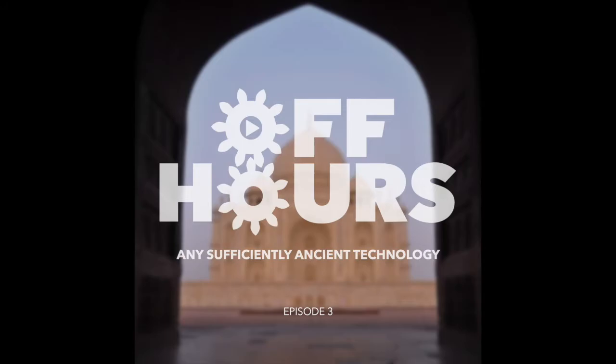Now, one of the other challenges that you end up having with cast materials is porosity. Yes, that's what I was going to ask next. Porosity is a problem where the metal isn't as dense as you want it to be. It could be because of gas. It could be because of voids. The metal just doesn't fill as much as you want, and so porosity can be a huge issue that you have to fight with. And again, it comes down to having the right parameters when you're casting, and that's primarily to do with the temperatures.